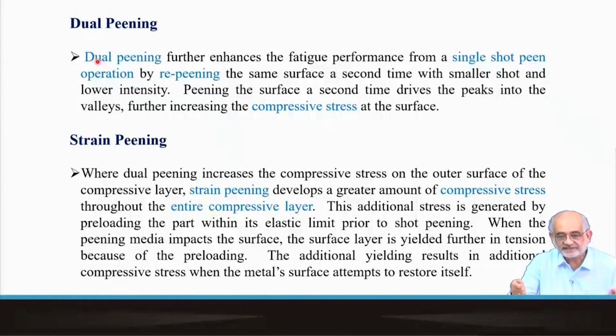If the material is already stretched, then the grains have already reached the limit of their elastic deformation. Now, if you hit it with an object, immediately you go into the plastic zone. So with a lesser amount of energy input, one can produce equivalent or even deeper subsurface deformation. And in the process, one can end up making deeper or higher magnitude residual compressive stress on the surface.